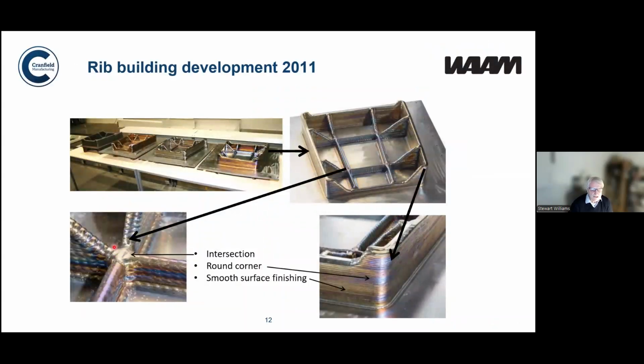Then when we moved that forward to titanium, we found lots of different problems. In particular, we had issues with cracking in certain areas. We had to work out how to deal with the intersection, how to manage corners better so we didn't get cracks and so on. So when you translate this rather simple concept of icing a cake with metal, it becomes much more difficult once you try and do anything useful.